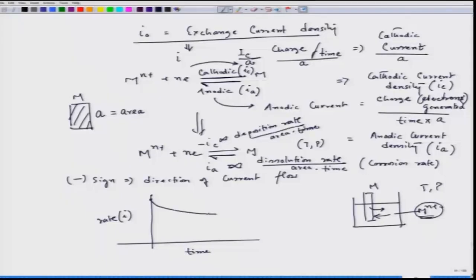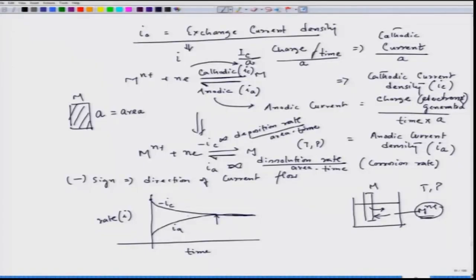So, initially this is the rate, which is let us say IC, and I am putting a minus sign because I am considering the direction of flow of that particular current, and it is a deposition. Now, the opposite current would also start immediately after putting that particular metal into that solution. So, this is IA, and then after reaching the same value, they will maintain that value if we do not disturb that particular solution. If you do not change the temperature, pressure, the metal surface quality is the same, the solution is the same, it will maintain that particular rate. So, this value indicates I0, which is the exchange current density. Now, interestingly, whenever we reach this equilibrium, do you get the dissolution or deposition to be different? No, they are the same.